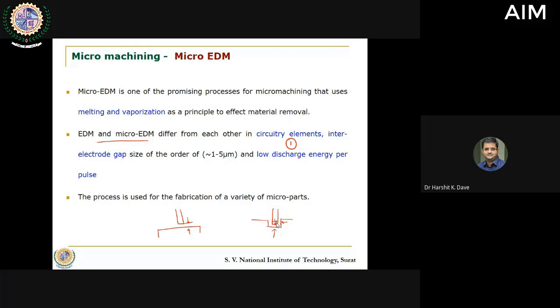And another important difference is related to the amount of energy that is being used per spark. So the discharge energy per pulse per spark is very less. It is almost 1,000 times less than what you have in case of EDM. So it is possible to generate even smaller features than what you generate in regular EDM process. So microfabrication with micro EDM is a very fantastic task.